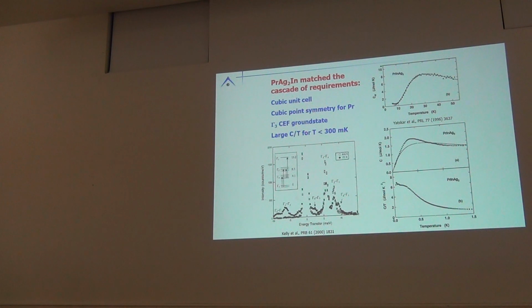Rosemarie Galera in Grenoble in the late 70s, 80s, was looking for singlet ground state magnetism in praseodymium, looked at this, did inelastic neutron scattering to see the CEF levels, and was disappointed because instead of a singlet ground state, it looked like a gamma 3 doublet, published a small conference proceeding and moved on. This is the hint that I wanted, that this might be exactly what I want. So we made it, we remeasured the CEF levels, we could confirm that we have a gamma 3 doublet, with about 6 meV to the first excited state, so below 60 Kelvin, I'm in a doublet ground state.